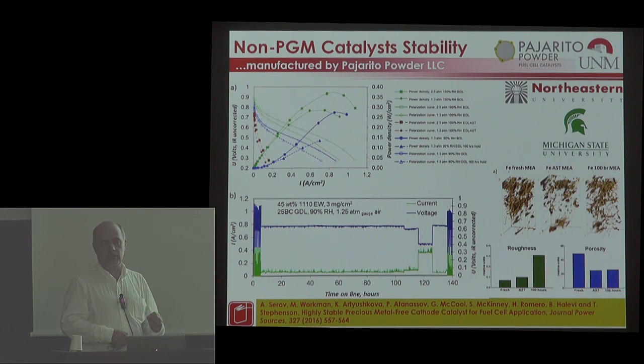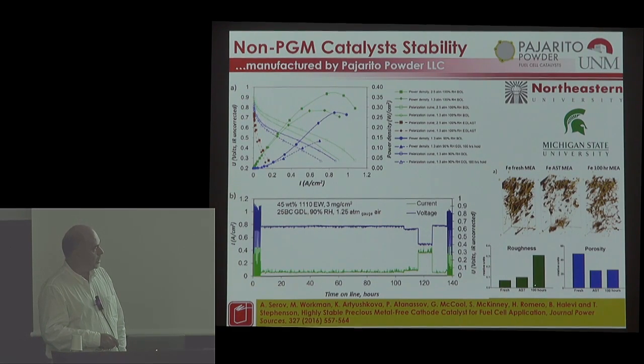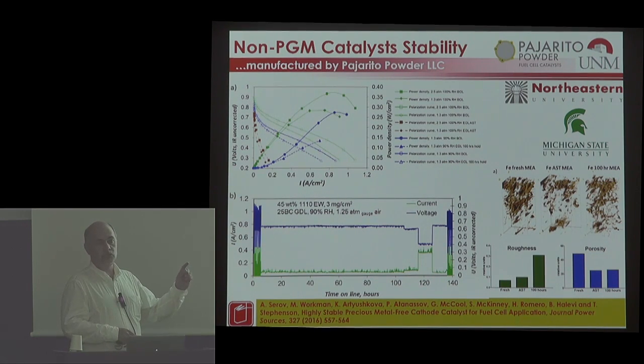If you translate it into the pore size distribution, it means that you are collapsing your mesopores and small macropores, and you're increasing your micropores by etching. And that is the pity of this catalyst, because what happens then, and it is not described in this paper, it will be described in the next paper, is that the flooding of the catalyst is directly proportional to the amount, or the volume, of micropores. So these two components of durability have nothing to do with what Frederick said. It is not the chemical stability of the active site. This is a materials durability.